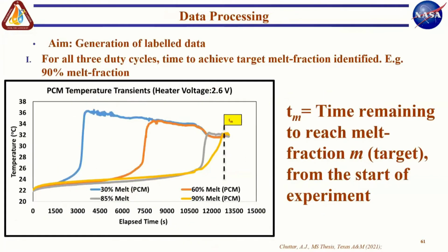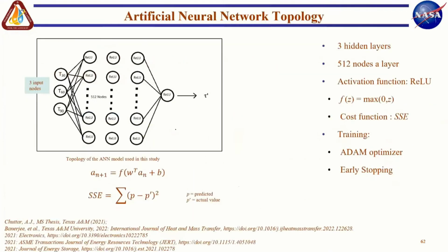So having all this data, we were able to come up with a label. So if Tm is the time remaining to reach a particular melt fraction M, so let's say I want to predict when it hits 50% melt fraction or when it hits 90% melt fraction. So the label for my machine learning was the time remaining to reach a particular melt fraction. And so we used this particular configuration of our artificial neural network topology.